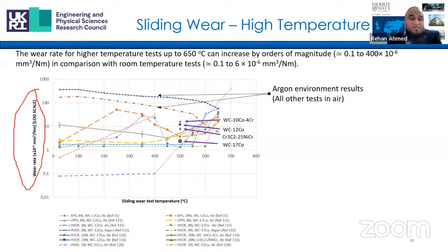The second factor, which is probably the more important factor, relates to the test conditions and the instability of the protective tribofilm. You see, WO3 or the tribofilm actually protects the coating and reduces friction and wear.